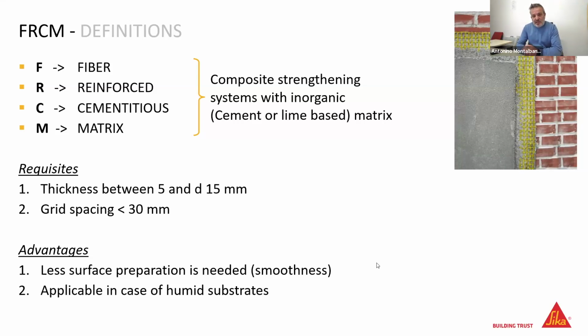So in this case, if you imagine a humid substrate, like when we work in a water tank or in a buried structure, the application of the classic FRP and the epoxy resin is still possible, but we need some special applications. So these systems are not a replacement and they don't go in direct competition with the classic FRP, but are systems that allow us to work in special application or service conditions.